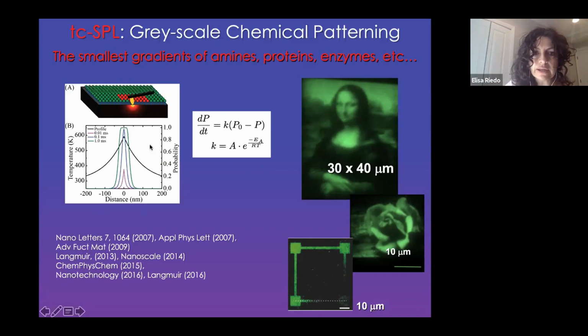And so you can really build a system of analytical equations that predicts, by knowing the dwell time, or the speed, which is essentially the same thing, and the temperature of the probe, exactly the probability that your reaction happens, which gives you the probabilistic amount of how many amine groups you have exposed. And so you can build complex patterns based on this. So you can have an input image, in this case a Mona Lisa image, and then you can use your equation and know in each point how fast or how high the temperature should be in order to expose a certain amount of amine groups.